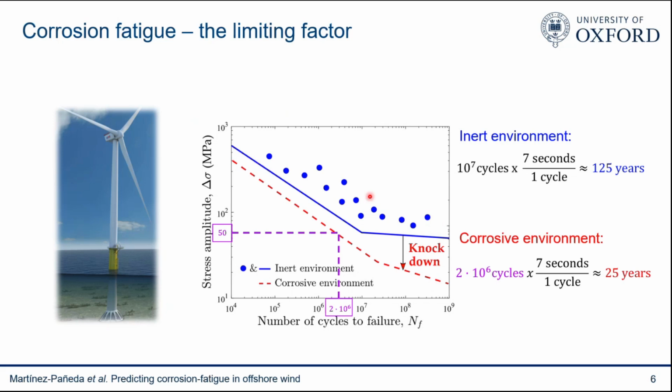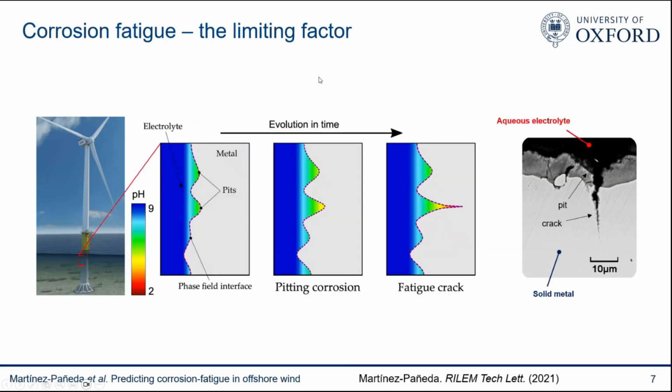Among others, this test assumes homogeneous 1D conditions, but corrosion is highly localized. Also, corrosion is a time and history-dependent phenomenon, but there is no time in here, and the history dependence means that we cannot use the superposition assumptions that are currently being used. But predicting corrosion fatigue is a complex problem, not yet solved in academic circles. So of course the industry had to move forward with something. They just couldn't wait for us to crack this problem.